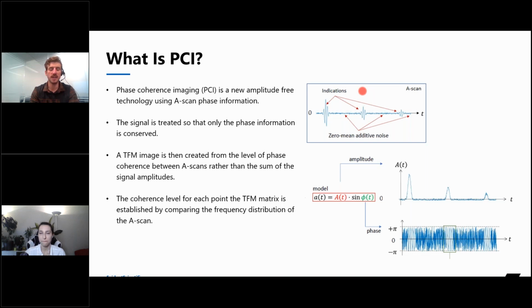But the main difference with phase coherence imaging is that rather than using the entire signal itself, we're going to isolate the phase portion of our signal. Each signal, each A scan, is made up of an amplitude portion and a phase portion. Put simply, if we take this times this, it ends up looking like this again. But for phase coherence imaging, all we're looking at is the actual frequency information of our signal. The big advantage is that it's a normalized or nearly normalized signal, and the amplitude is not taken into account once we look at the final image.